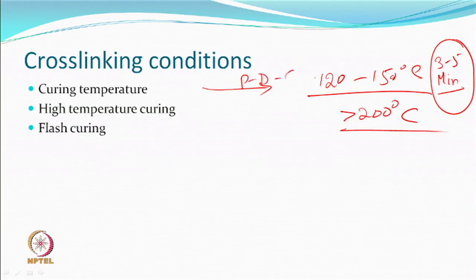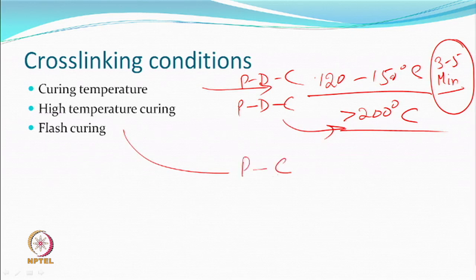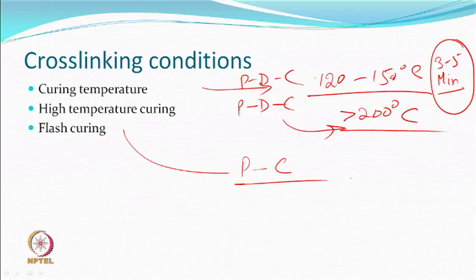So high temperature curing is actually pad dry cure, this also is pad dry cure, but at higher temperatures. There is another term which is called flash curing. Their aim was that, well, if you're going to high temperature, drying will also take place, right? But people would prefer a drying step in between, because at a higher temperature, the rate of drying is very high. In some sense, it is good. But because of that high rate, some of the chemicals can migrate from inside to the surface as they are coming. So, migration in the wrong direction. So, you have a non-uniform cross-linking. If you have a non-uniform cross-linking, you can understand what will happen to the properties.